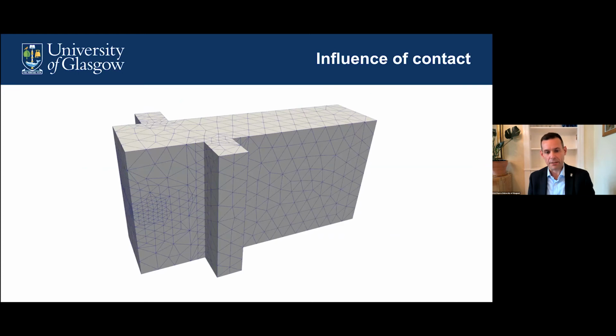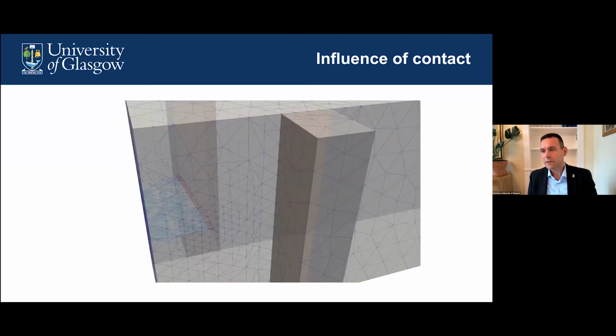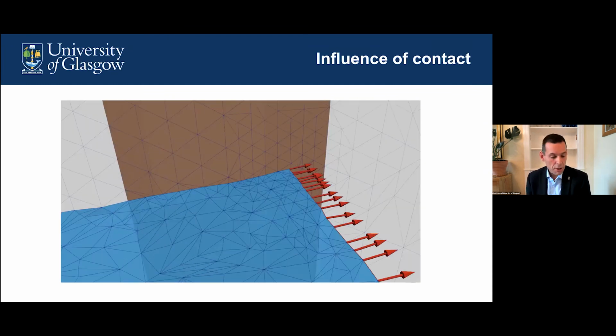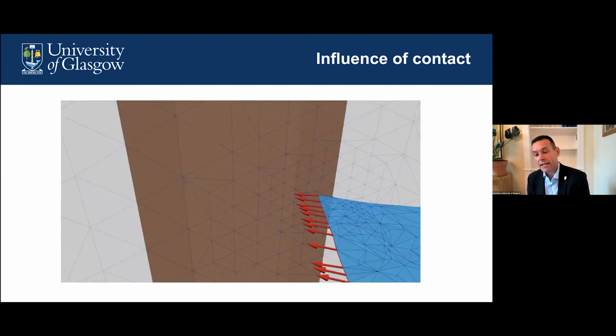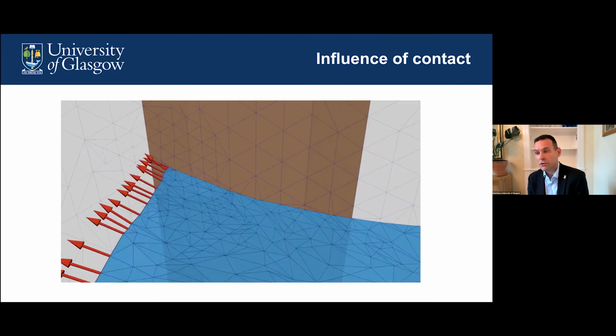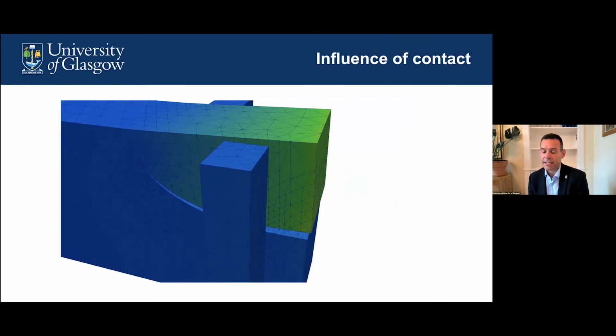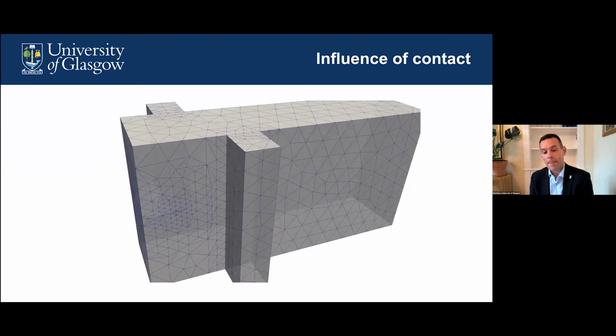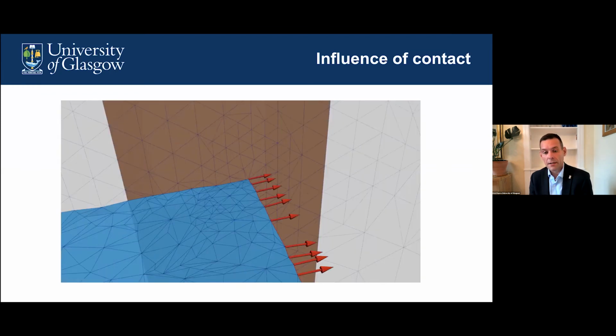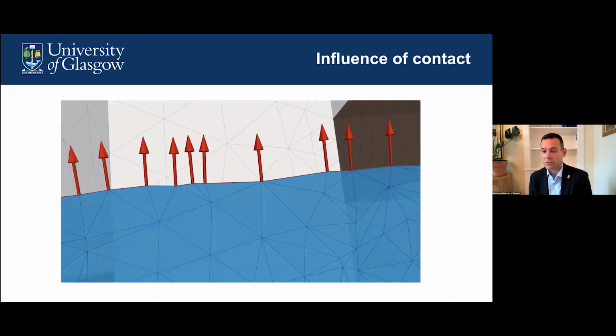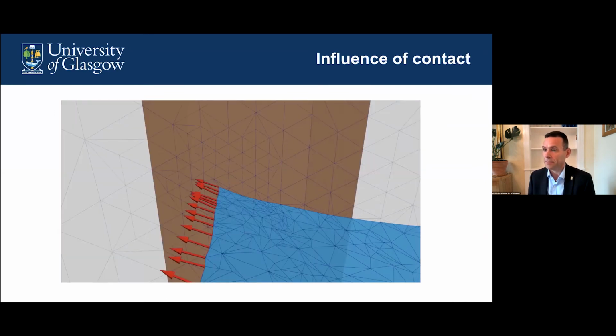So in this particular example, the top and bottom of the sample are being pulled apart after a crack is initiated, and laterally it's being compressed by external pressure. As you can see here, the crack nicely is able to negotiate that contact surface. And you can see the interplay between the contact surface and the crack propagation.